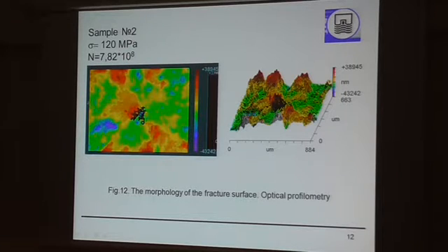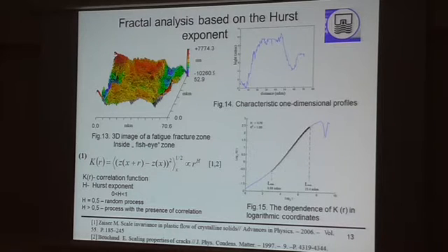We used a new interferometer profilometer for quantitative fracture surface analysis, which provided data allowing us to find correlation between mechanical properties and scale invariant characteristics of damage-induced roughness formed under high and gigacycle fatigue loading conditions. We used the method proposed by Zaiser and Bouchaud. The method is based on analysis of the relief of the fracture surface, which exhibits the property of self-affinity as manifested by invariant characteristics of surface relief.